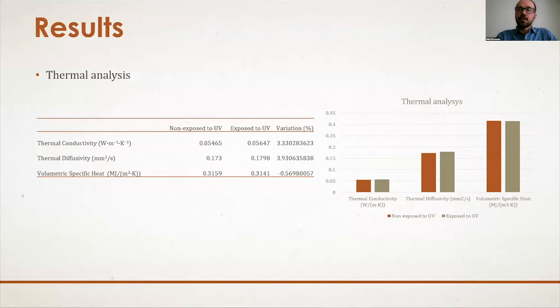Regarding the thermal analysis and focusing on the typical application of cork composites as a thermal insulator, as it is possible to confirm by its thermal conductivity, diffusivity, and volumetric specific heat, we can verify that there is some degradation of its thermal constants. So the conductivity and diffusivity of samples exposed to UV increased, while the volumetric specific heat decreased. Although this means that the specimens exposed to UV have a lower capacity as a thermal insulator than the non-exposed ones, the variation is very small and the degraded composite can continue to be used as a thermal insulator. So this was the main conclusion from the thermal analysis.